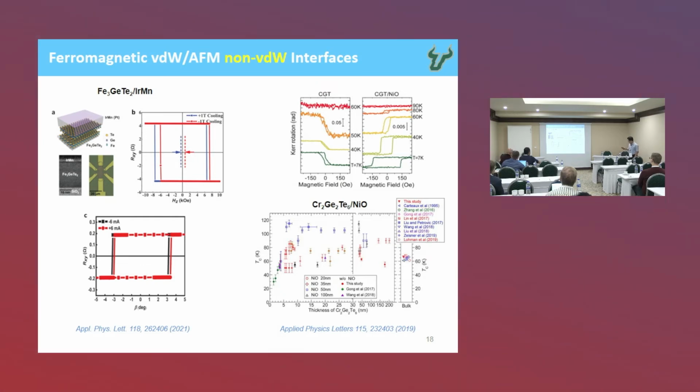However, what we consider here is that nickel oxide has a Néel temperature way higher than room temperature. So eventually, when you form the interface with this one, which has a TC of just like 60 K, way lower, then when they perform the magnetic measurement, the magnetic hysteresis loop, in the temperature regime where they look into it, they would not be able to see the shift. Then people can argue why they observe the exchange bias in this particular case.